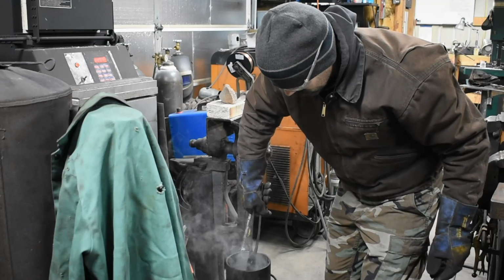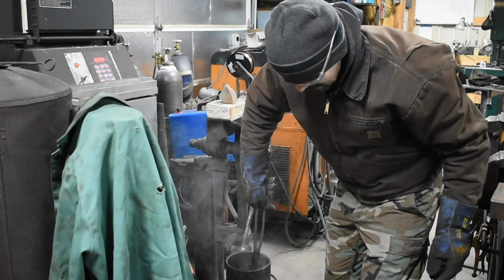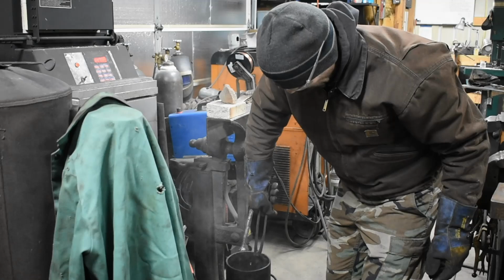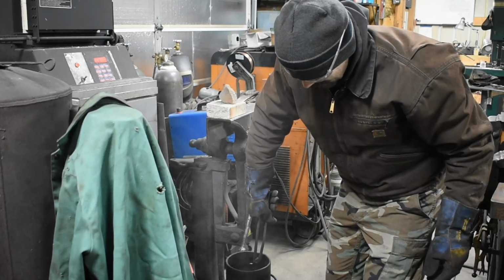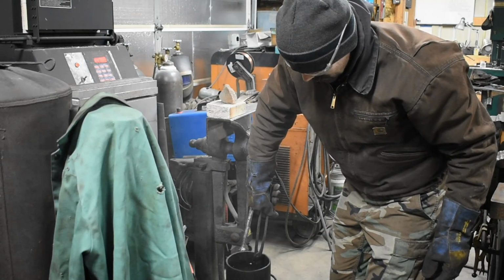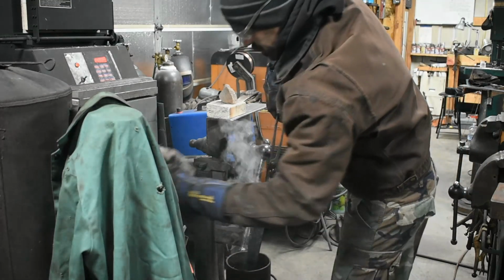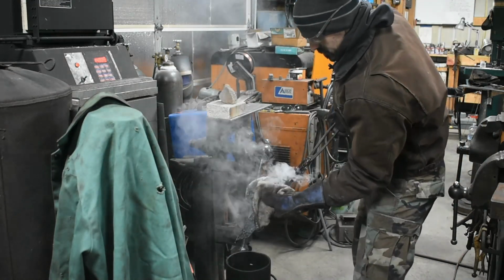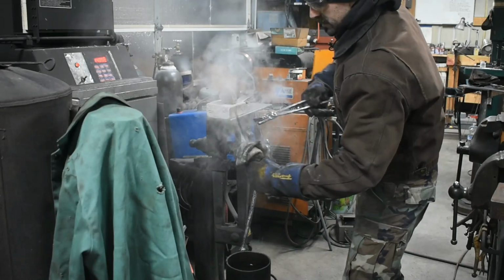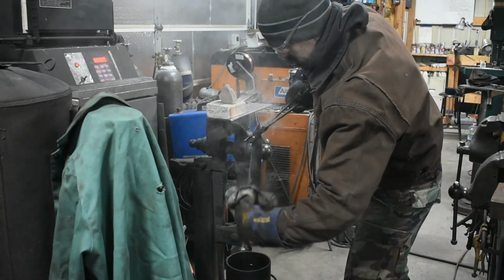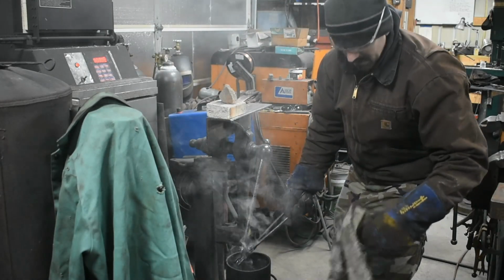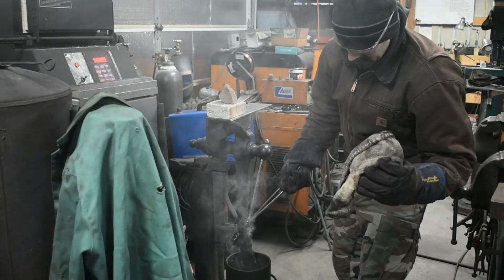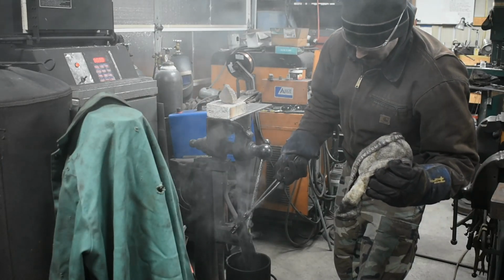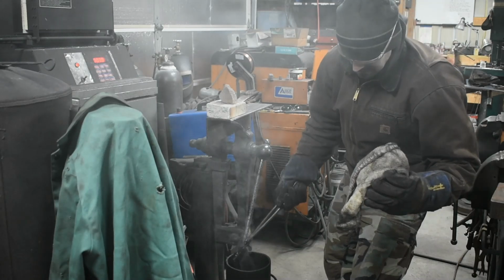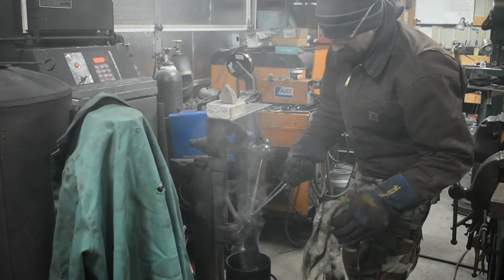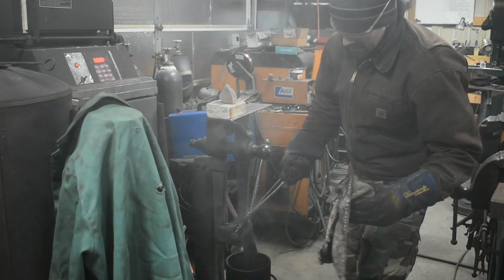Gotta get in there nice and quick and agitate it up and down, back and forth, not side to side. And pull it out once I've got down past the pearlite nose all over, but I'm still at several hundred degrees, smoking hot. Flip it over, give the bolster some extended quench time because I don't want the added thermal mass of the bolster getting any auto temper down into my blade.